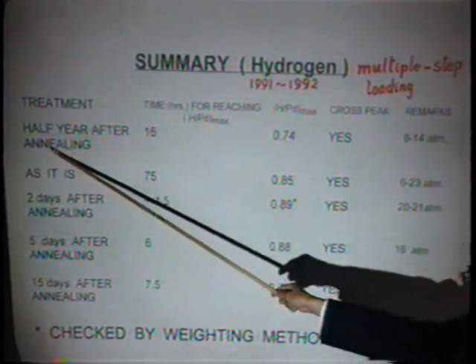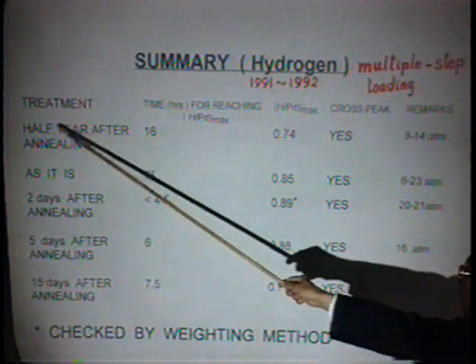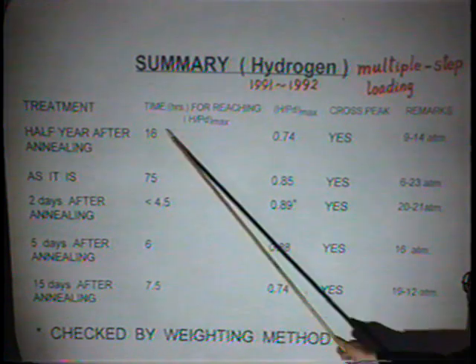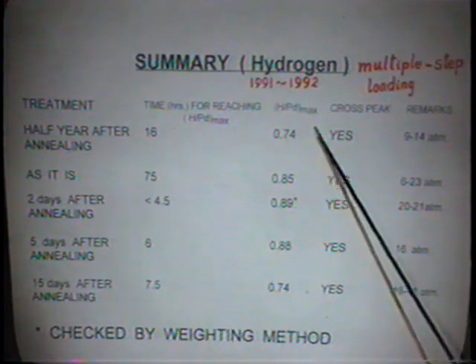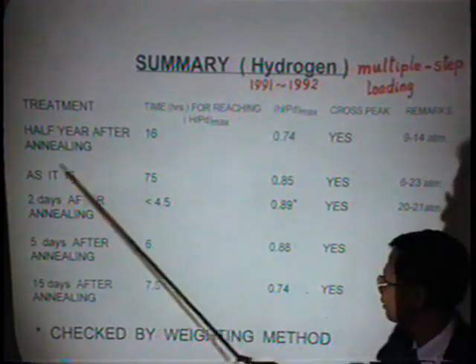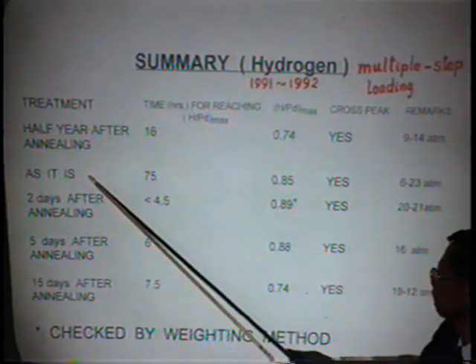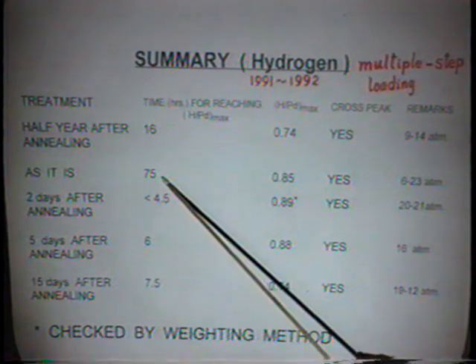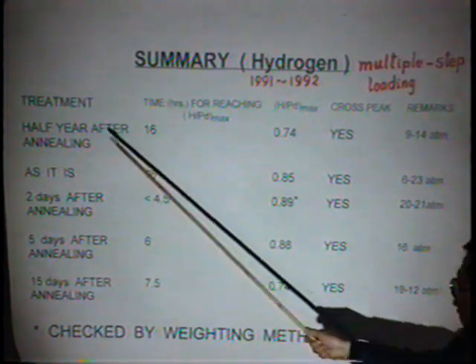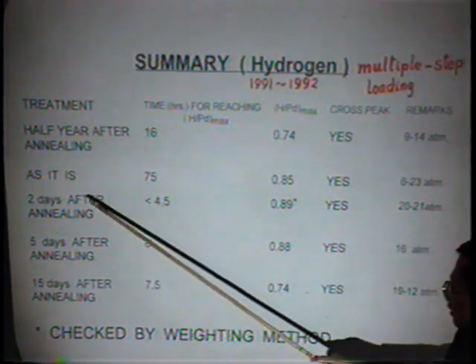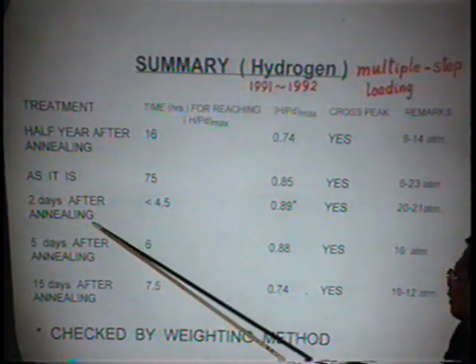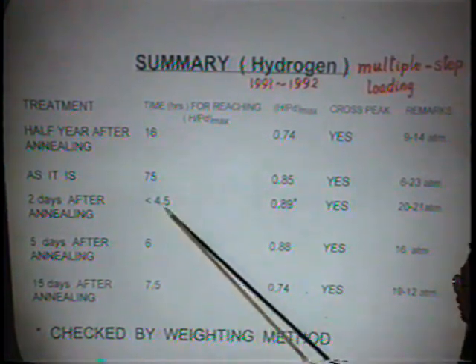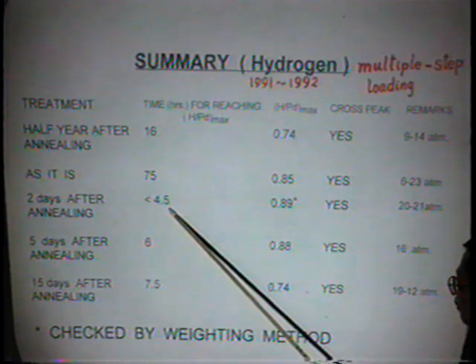The first sample we treated is the annealing method. Then after half a year, we did this experiment. It needed about 16 hours to reach this maximum value. But if we do not anneal it, then we need 75 hours. But if we anneal it, 2 days after the annealing, then it's very quick, less than 4.5 hours.